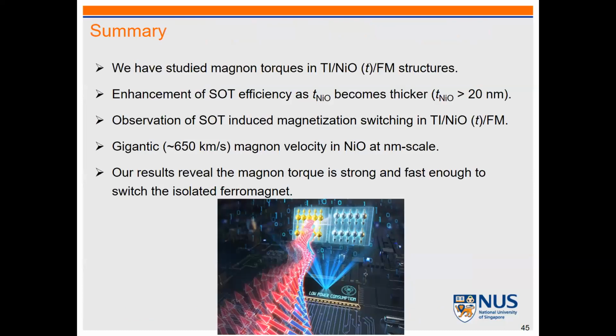Okay, so as a quick summary, we studied the magnon torque in this structure. We have some enhancement of the spin-orbit torque efficiency as we use more than 20 nanometer nickel oxide. And the magnon propagation velocity can be very high, more than hundreds of kilometers per second. And finally, we also show it is possible to switch the PMA, but with a small magnetic field. So basically, this magnon torque is strong enough and fast enough to switch the isolated magnetic structure.